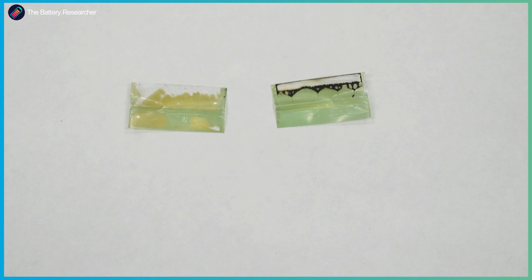At first we were a little disappointed because this is not even an active component and we did so much work, only to find it's this silly tape. But as it turned out, this tape is pretty standard in the lithium ion battery cell industry — a lot of companies are using it. This is basically what made my work so prominent: it generated media hype because it's an easy-to-understand message — tape leads to self-discharge — and it's an actual problem for many cell manufacturers. We're also especially proud that it's not only a media hype; our professional colleagues are looking into it, and both papers are ranking number one and two for most read in the Journal of the Electrochemical Society for a full month already.